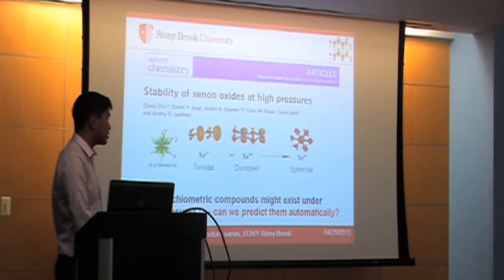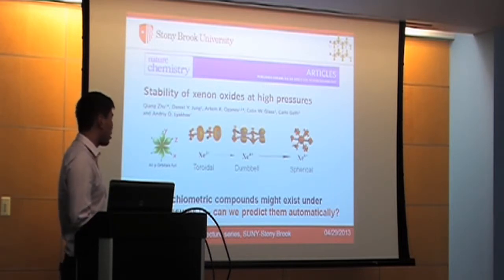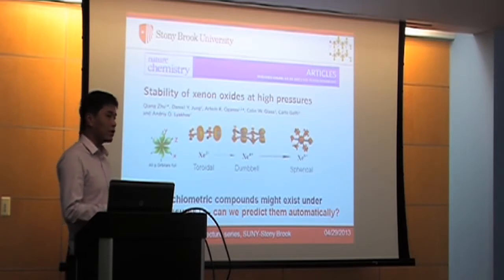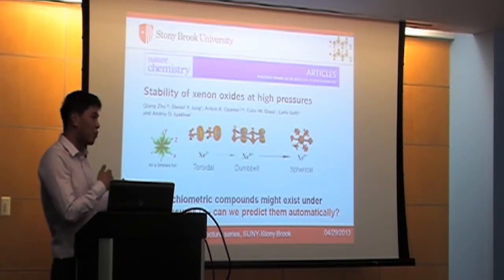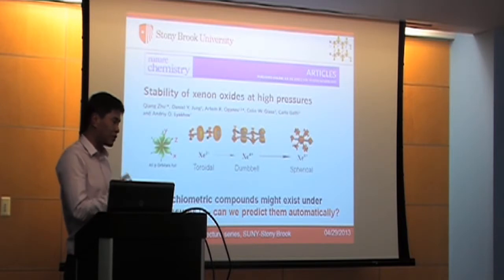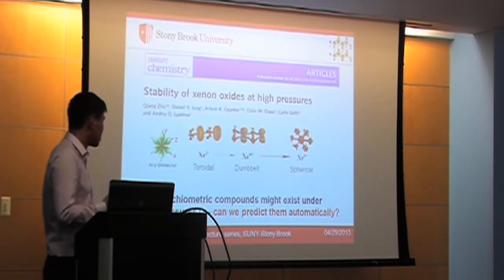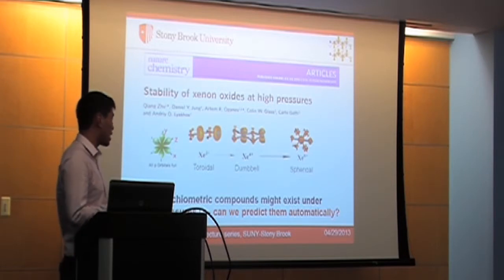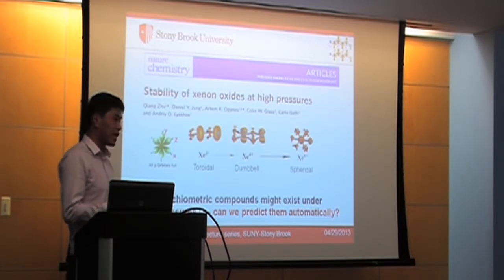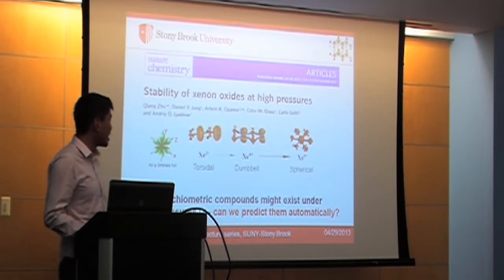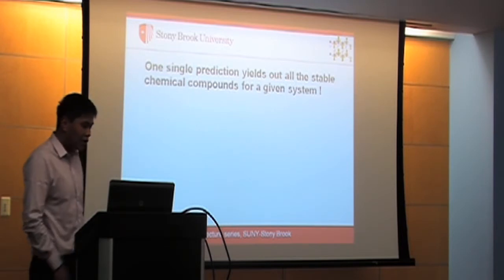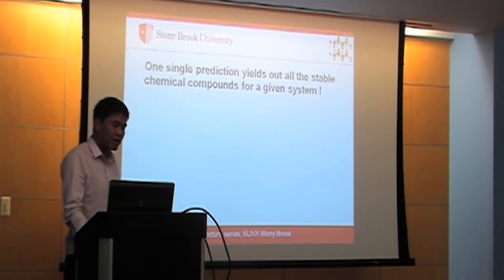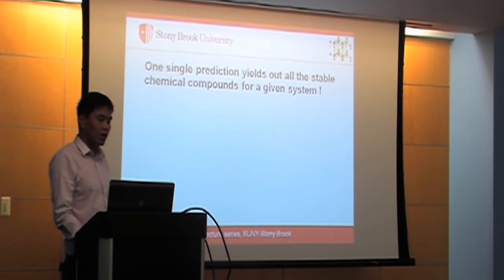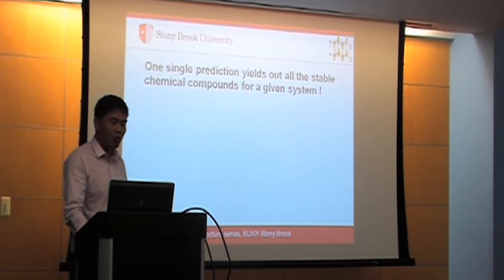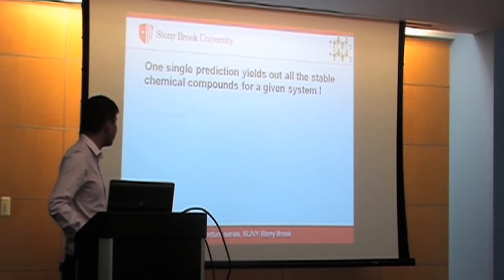So the problem is how can we predict the stoichiometry? For the xenon oxides, we learned the hint from the ambient pressure behavior. We know that xenon might form +2, +4 to +8 valence states, so that we can figure out the possible chemical composition for xenon oxides. But if we don't know this information, can we predict them automatically? The answer is yes. So we designed a method which can use just one single calculation. It can yield all the stable chemical compounds for a given system.